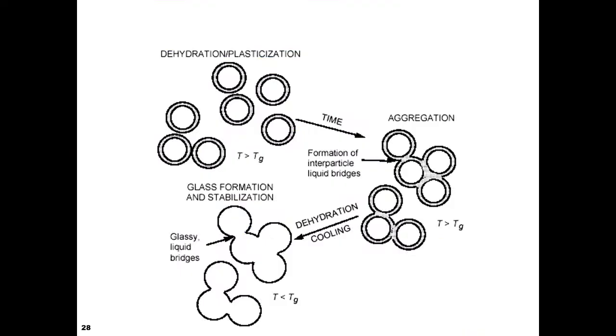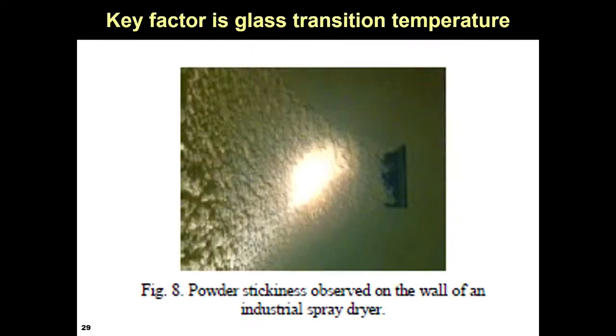So some powder, at ambient temperature, absorbs water, the powder aggregates, and then makes some large particles. Therefore, when we make the powder, the moisture content is important. Also, the environment temperature is important. When we store the powder, the moisture absorption behavior is important. So, in spray drying, please remember the raw material's glass transition temperature. The key factor is glass transition temperature.